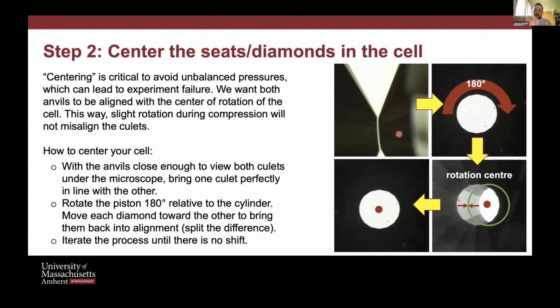And so to test, you do a 180-degree rotation just to see how bad it is. And as long as you're pretty close, you should end up with something that looks like, I think, the bottom right picture, which is where you have misaligned culets that are clearly not overlaid anymore. But that's telling you, you can work back from that and say, okay, well then the rotation center was not at the center of the culets. That would have been nice. My job would be done now if it was, but it's not. That means I need to move my culets, and of course you need to move both of them. And so basically you split the difference, and you want to move them both back halfway towards the other one. And then in theory, you should then be on the rotation center.